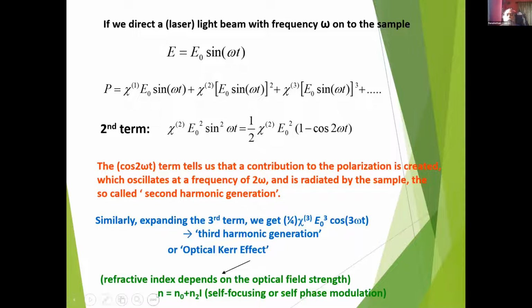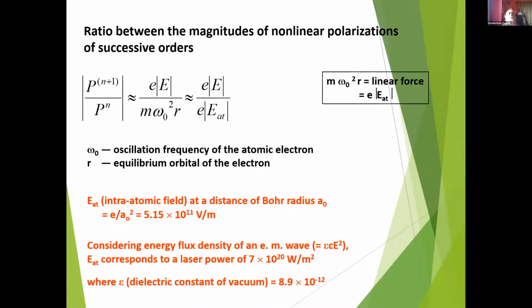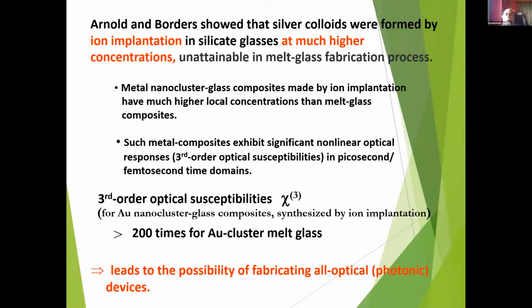And the total refractive index is n0 plus n2 I, where n0 is the linear part of the refractive index, and n2 is the nonlinear part of the refractive index multiplied by the intensity of light. Now, I have to skip many things. First of all, we have seen that when you are implanting metal particles in the glasses, you are getting an enormous amount of metal particles. You can embed innumerable millions of metal particles in the glasses, which you cannot fabricate by chemical doping or by chemical process. Okay, so metal glass composites made by ion implantation have much higher local concentrations compared to the melt glass fabrication process. And such metal composites exhibit a significant nonlinear optical response, that is the chi3, in the picosecond to femtosecond time domain.